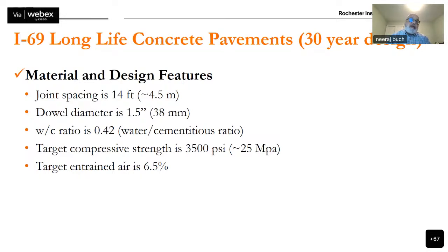The dowel diameter for the long life concrete pavements was about 38 millimeters or 1.5 inches. The water cement ratio, the water cementitious ratio, actually, because there were pozzolans that were used in the production of the concrete mix, was approximately 0.42. The compressive strength was targeted about 25 megapascals. Now, in the United States, we don't use cubes. We use concrete cylinders. So this is cylinder strength, not cube strength. And the target entrained air was about 6.5%.